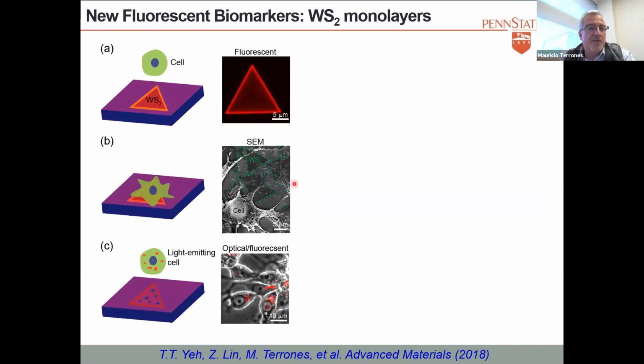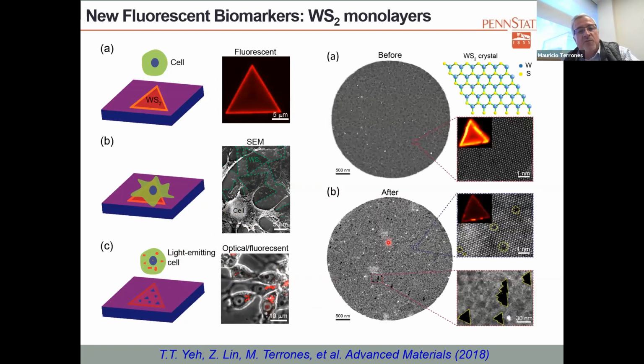So what happens is that you basically grow your tungsten disulfide triangles. You put your cells, and you can see the cells here, and then you have the triangles here. And after some time, you remove the cells, and they have ingested the fluorescent material, and you can see that they are shining. I will show you some more imaging. So this is the material before and after the cells have ingested the triangles. You have a nice photoluminescence, you have nice images, but after ingestion, you can see there are vacancies, and these are sort of extended vacancies like triangles, right? So it's like the cells are eating Doritos, right?